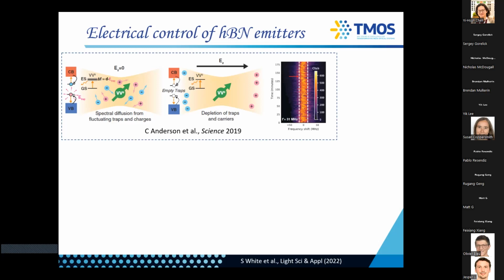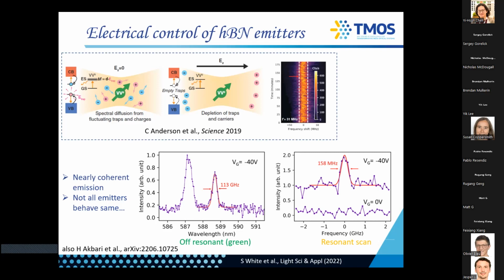In their case, it actually works quite well. They eliminate the charges, and then you get very narrow lines, about 30 megahertz, basically Fourier transform limited. If you take the analogy to our case, we of course don't have a PIN junction, but under very negative bias, we do have a depletion layer, essentially. Under negative bias, we can look at the emitters, and they are very stable. The line width is spectrometer limited when you pump off resonance, and when you do an on-resonant scan, you really get these 160 to 100 megahertz lines, which is basically Fourier transform limited, from these emitters.